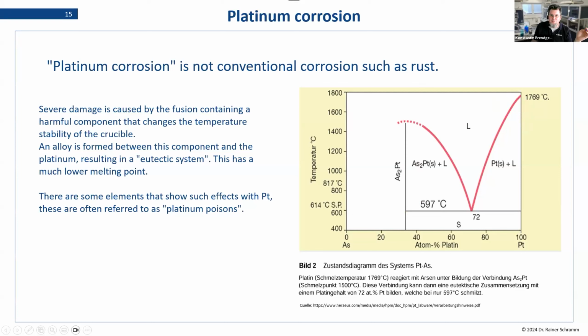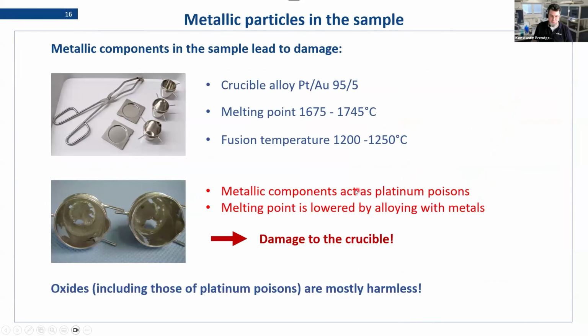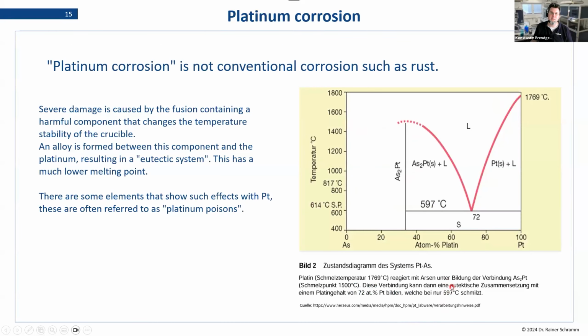and I'm actually in the way here. I just need to move that. You see, so pure platinum would have a melting point of roughly 1,700 degrees. And now if we mix this with arsenic, the melting point drops down to like 1,400. This is a steep drop already. But now the problem is, if that one alloys with platinum, the actual melting point is down here. It's only 600 degrees. So we have kind of cascading effects, and our fusion actually happens in that temperature range.